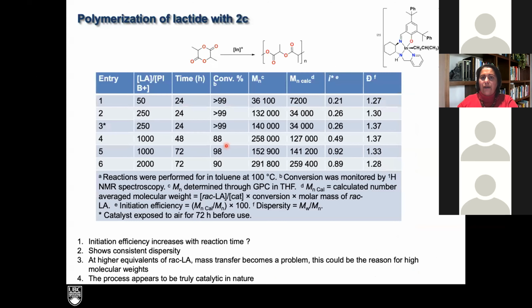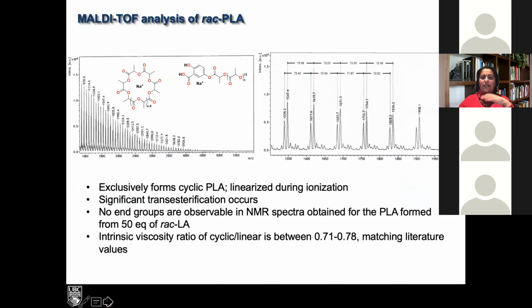What Tutura found was that he was able to get really high molecular weight polymers with initiation efficiencies that started getting better with reaction time. The dispersities were fine, and it seemed to be a catalytic reaction. But the interesting thing about the system is the polymers are all cyclic polymers. So he was able to get high molecular weight cyclic polymers. These are materials that are really difficult to get. Just for entropic reasons, to get the two ends of the polymer to come together at high molecular weights is really, really difficult. And that is what he was getting. It was really exciting for us. We were like, what is going on here?